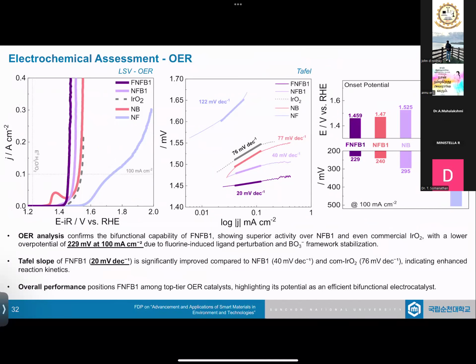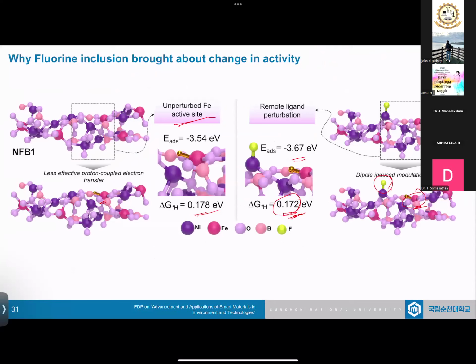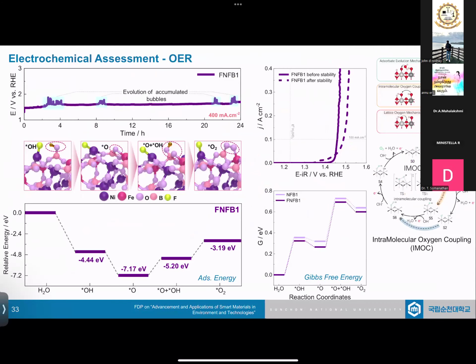We evaluated the material, and we found the Tafel value, and we thought that this might be an adsorbate evolution mechanism or a lattice oxygen mechanism. But the problem is, we need to prove it, because we felt with respect to the Tafel value that we got, it should be an AEM process or an LOM process. But when we started evaluating it, we found that because of the vacancies present and because fluorine is present in the system, we didn't get an LOM process or an AEM process. What we got is something called the intramolecular oxygen coupling process, where two different sites are involved in the reaction.